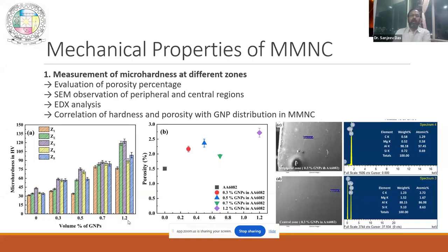Now for an alloy system, what happens? The solute is basically rejected towards the center, and when the solute is rejected to the center, it increases the hardness at the center. Now the same thing is happening with the nanoparticles also. So you are uniformly distributing them, but some amount of GNPs will be pushed because their size is very small. So the solidification front is basically pushing some of those GNPs, not all, to the center,